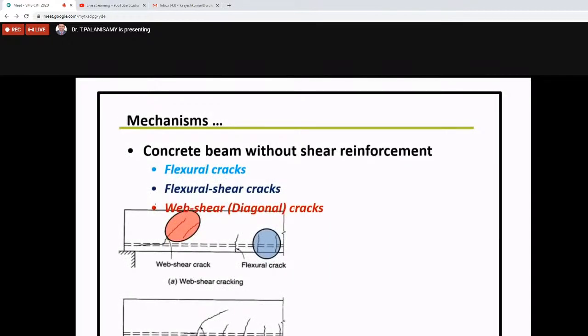Now, this is the source of this figure. A concrete beam built without shear reinforcement fails in a lot of cases. You can see some flexural cracks, flexural shear cracks, and web shear diagonal cracks also. So you can add this kind of fiber. It reduces this kind of failure in the system. The flexural cracks, flexural shear cracks, and web shear diagonal cracks you can also rectify.